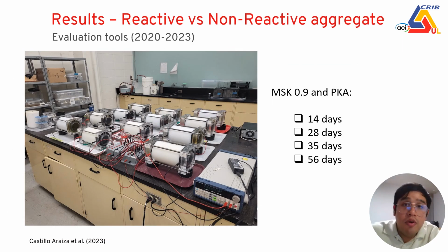As I mentioned in the slide before, we do this testing for two aggregate materials, one reactive and one non-reactive. The reactive one we identify as MSK 0.9 and the non-reactive material is PKA. These aggregates are similar, not the same, but similar, to see how the performance of each is going to be after the electrochemical treatment after 14 days, 28 days, 35 days, and 56 days, and see if we can find, as I said before, a measurement that can allow us to distinguish when we have a reactive and when we have a non-reactive material, or if we can evaluate the potential oxidation reaction of this type of concrete materials.